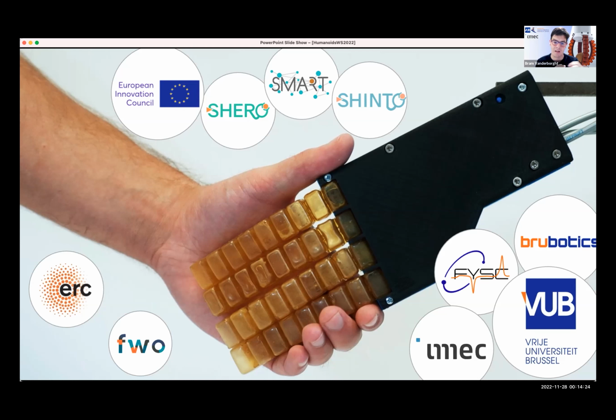The big difference with thermoplast is that when you typically print a material layer by layer in the Z-axis, the material is weaker in this direction than along the filament in the other direction. So you create anisotropy in your material. But here we have reactive printing: when the material comes out of the nozzle, there is a chemical reaction taking place. That means that the material is covalently bonding also in the Z-axis, meaning that you create very strong mechanical chemical bonds, and that means that we have no anisotropy in our material, so it's as strong in all directions.